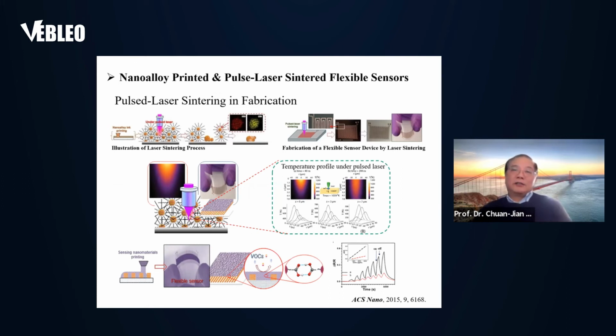And now another technique is using a laser. With a laser, you can introduce high temperature, but it's highly confined, localized temperature, as illustrated in the middle here. This profile is a simulation to look at the temperature profile region. This red zone, as illustrated here, is really only in the thin film nanoparticle area. There's no penetration to the substrate, so you can nicely control that.